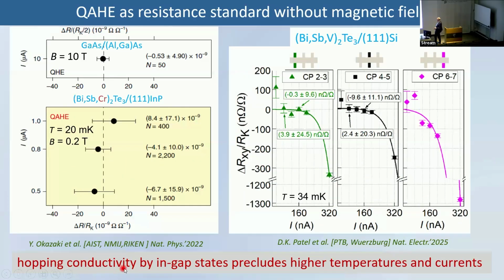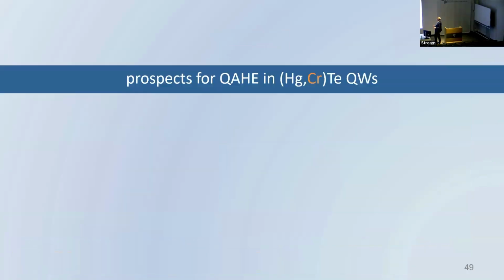The reason is that there are impurities. Again, there are impurities between this conduction band and valence band, and these impurities give rise to additional conductivity by hopping, additional parallel conductance, and kill quantization precision, except if you are at very low current at very low temperature. And now, maybe you can find a material with a better concentration of impurities, which pins the Fermi energy but gives less scattering. And we have made calculations for chromium doped mercury telluride.